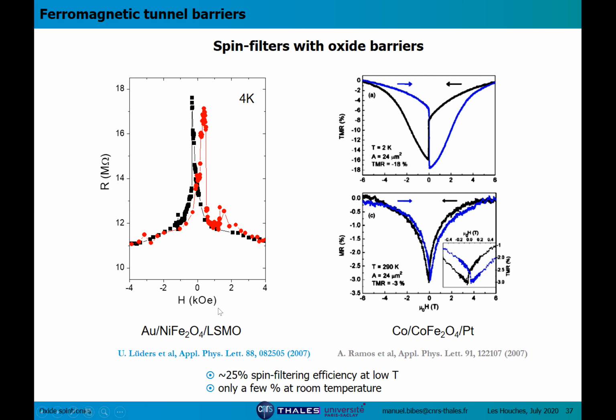So here, these are some results combining LSMO, nickel ferrite, and gold. You see a TMR curve of about 50% TMR. This is with cobalt ferrite and cobalt and platinum as the non-magnetic electrode. And this was at low temperature, and here there's some finite TMR at room temperature, about 3%. So it works, but the efficiency is not great, possibly because of growth issues to grow these very thin layers of spinel ferrites.